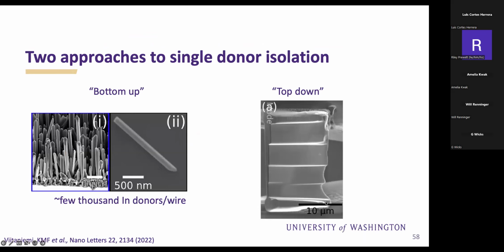So in parallel, what we also did was we carved out a very thin sample out of our bulk zinc oxide, where the layers go from about 500 nanometers thick up to a few microns thick, with the hope that we would be able to isolate single indiums.